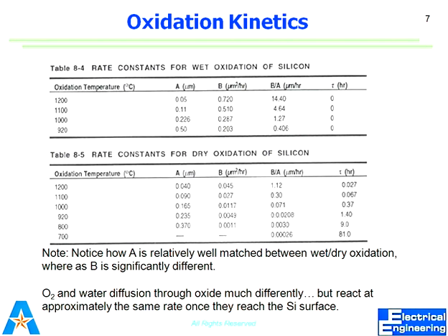So what they actually do, if I have 1000 nanometers, meaning 1 micron, first 200 nanometers, or first 100 nanometers, would be dry oxidation, just to have a better quality, to have a better isolation. Then I quickly do wet oxidation and grow up to 950, and for the last 50 again dry oxidation.